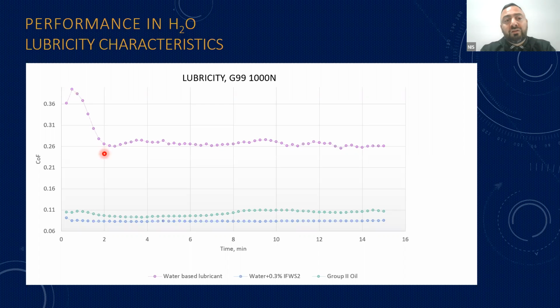So you can have what I initially said, a sacrificial area. It works for some applications, but if you're talking about metalworking fluid, it doesn't work that way, because in the G99 test you have the same track. You're running over and over the same track for 15 minutes, and of course, it generates tribofilm. In a real application, when you're cutting some piece, you always have a fresh surface. You don't have the luxury to spin on the same area. You need to cut and just move on to cut the next area of the piece. So in that application, your friction is going to always stay high.